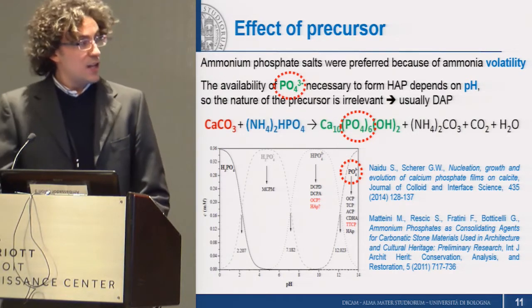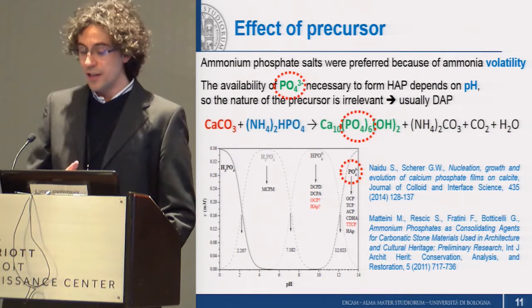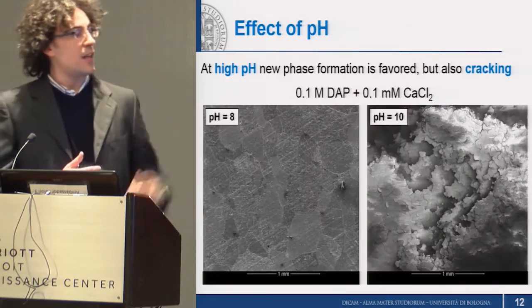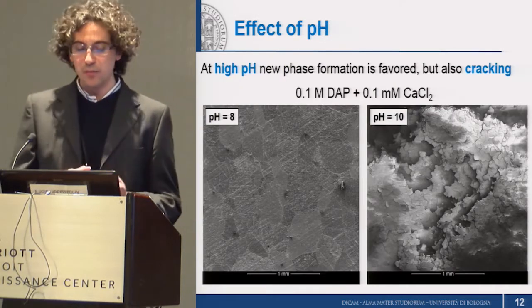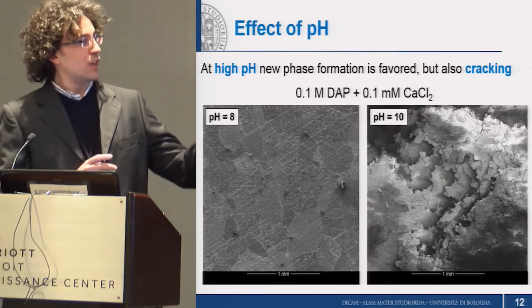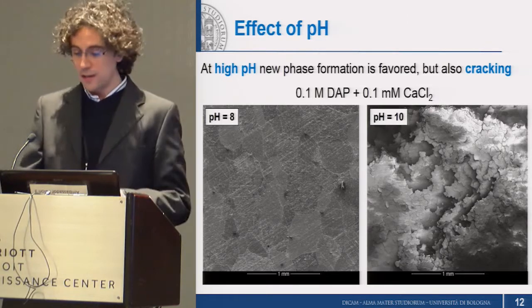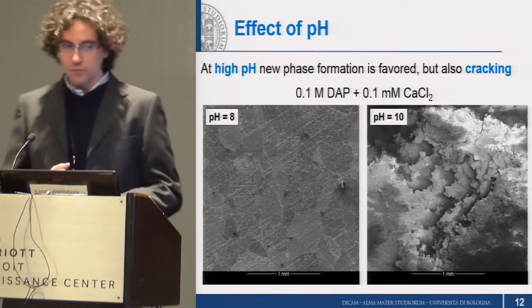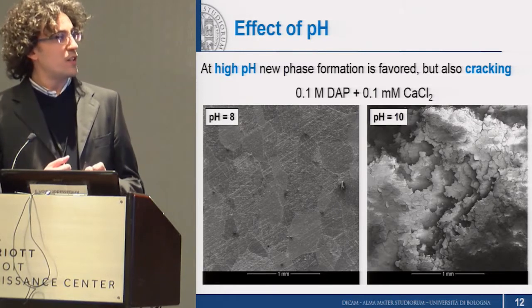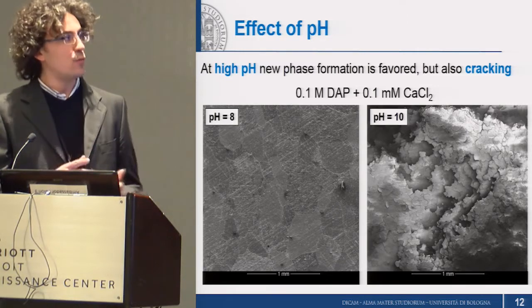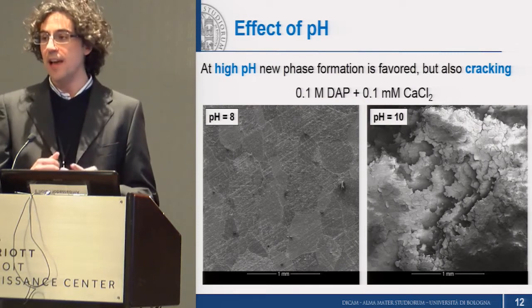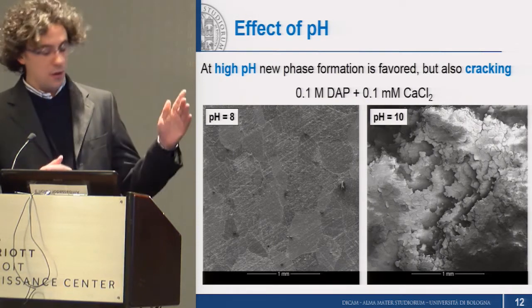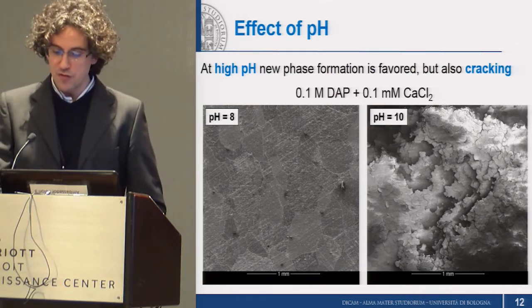So in terms of pH, this has a very strong influence, as you can see, using the same concentration, the same salt, by simply increasing the pH from 8 to 10. So quite a lot of new phases, new material form, but this turned out to be heavily cracked. So in the end, our attention focused on almost neutral pH values.